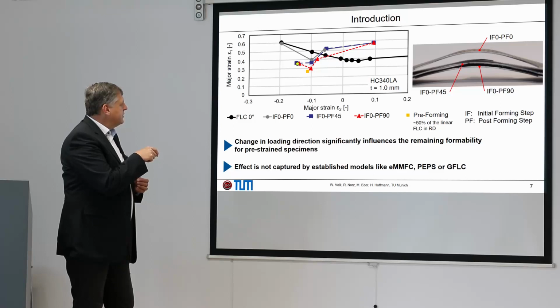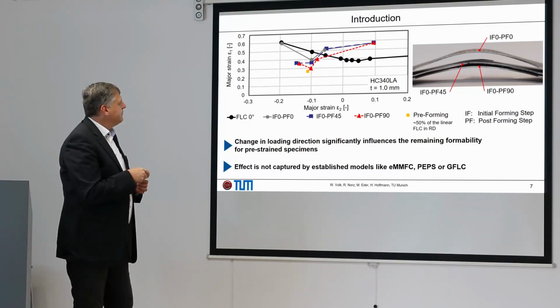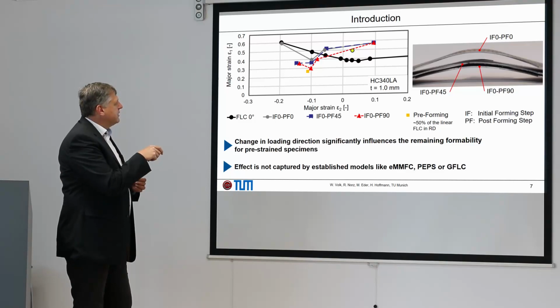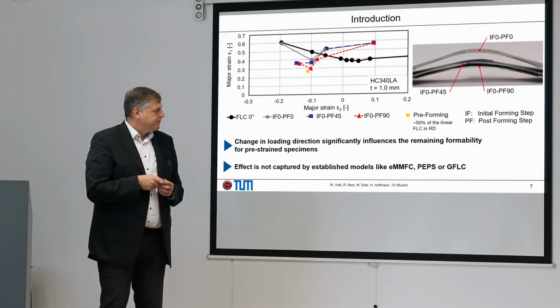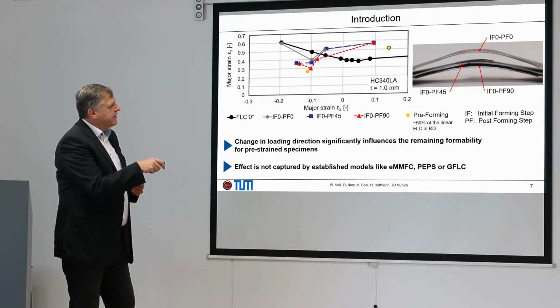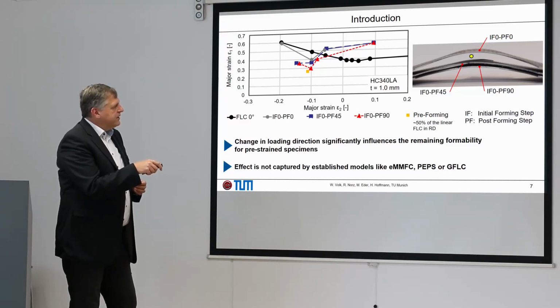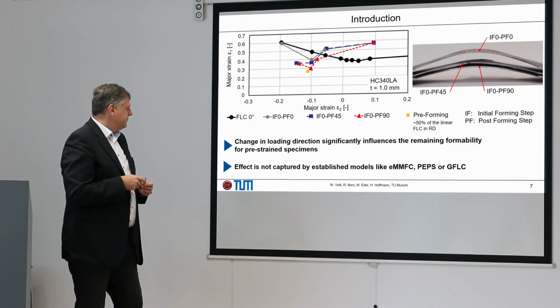Here it's also in uniaxial. We are losing much formability. In plane strain, it's not so critical. And when we go to biaxial direction, it's nearly the same. We can also see it with the heights we can reach, that here the 0-0, here 0-45, and 0-90. These are these 3 points.